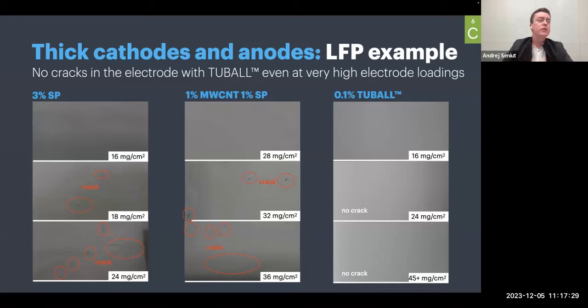Obviously, this result might not be directly applicable for EV recipes, even though we have customers who are trying to maximize the thickness of the electrodes, the loading of the electrodes, to 40 milligrams per square centimeter on one side. But this can be easily applied to ESS applications, because in this case, your battery doesn't need to charge and discharge that fast, but energy density and economy is crucial.